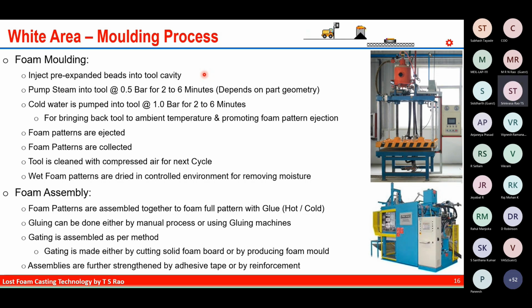This cold water has two advantages. One is to bring the tool back to ambient temperature, and second is promoting the foam pattern ejection from the tool. After the cold water is pumped, the foam patterns are ejected from the tool. Then foam patterns are collected by hand. Then the tool is cleaned with compressed air for the next cycle.